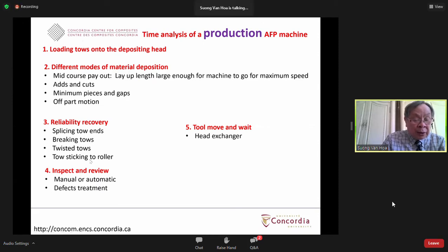Then another activity that the machine has to spend is inspect and review. After you deposit the layer, people have to make sure that it's okay, so they have to do inspection. Now, it depends on whether the inspection is manual or automatic. If it's manual, it takes a lot of time. I will mention that later on. And then after you found the defect, you have to decide the treatment of the defect. If the defect is not that severe, you may neglect it. If it's critical, you have to repair it, or maybe it's too bad, you may have to reject. And another item here called the tool move and wait.